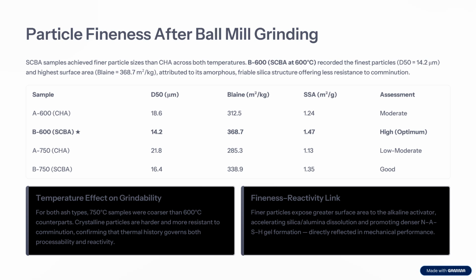The temperature effect on grindability for both ash types: 750 samples were coarser than their 600 counterparts. Crystalline particles are harder and more resistant to comminution, confirming that thermal history controls both grindability and reactivity. Finer particles expose greater surface area to the alkaline activator, accelerating silica dissolution and promoting denser gel formation, directly reflecting the mechanical performance.